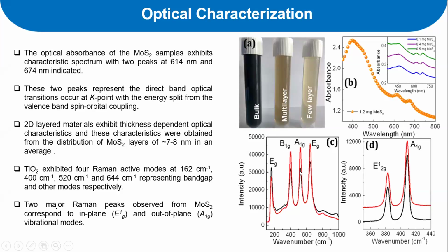And further confirmation is in the Raman spectroscopy. Basically, the titanium dioxide exhibits four Raman active modes at 160, 400, 520, and 644 inverse centimeter, which clearly shows the anatase phase of titanium dioxide. And further, we have observed two optical modes here, E2g and A1g, that correspond to the moly sulfide in-plane and out-of-plane vibration modes, which confirms the presence of moly sulfide on top of titanium dioxide.